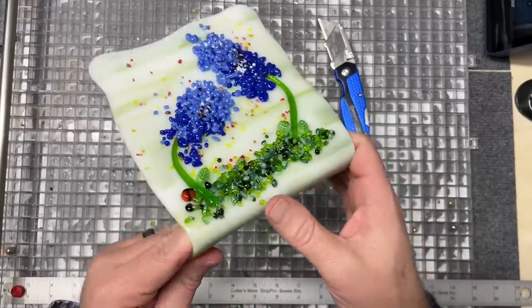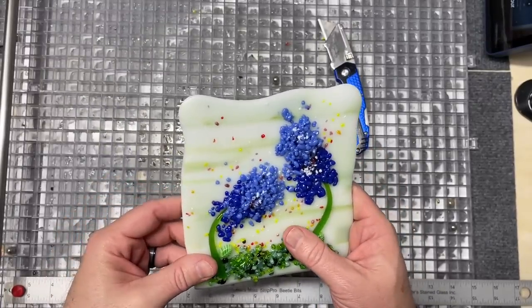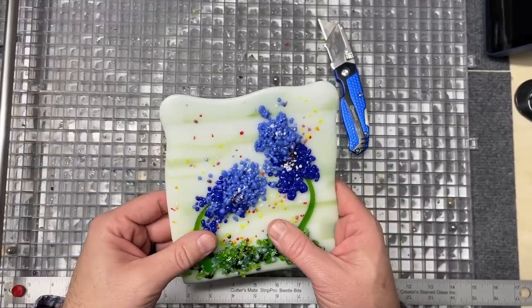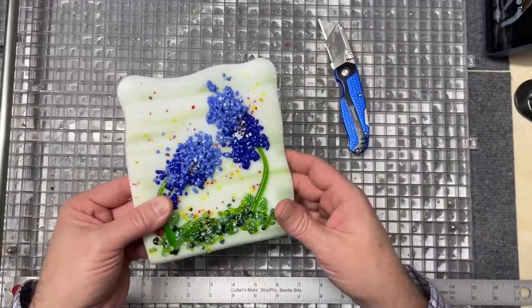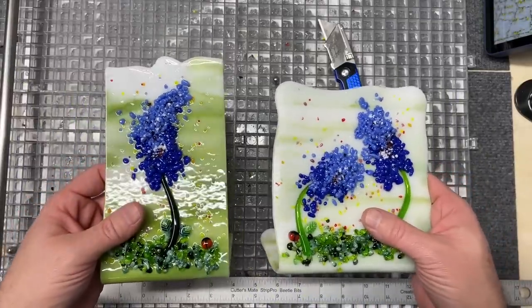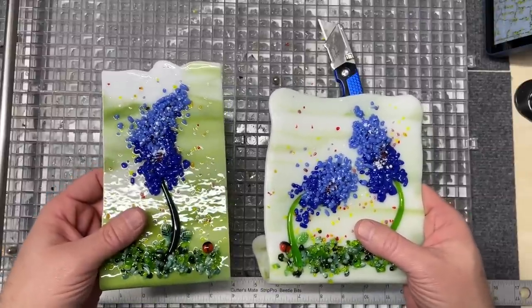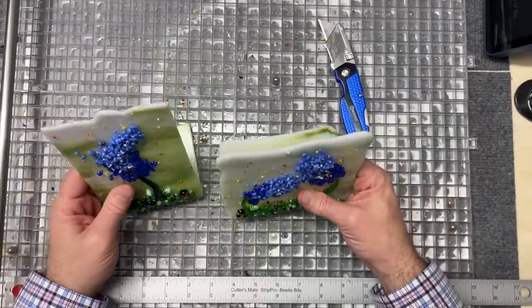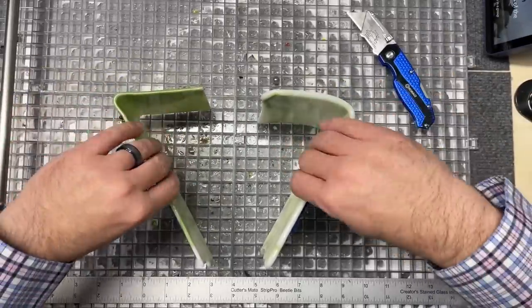We're done — here is the self-standing piece, folded over quite nicely. My firing schedule will be in the video notes as always. I have to admit when I opened the kiln I had a little bit of a panic attack — that's a stainless steel former and I forgot to put any kiln release on it. I usually put fiber paper down but totally forgot. Neither piece stuck though, so I lucked out. It was a low slump temperature, about 1200 degrees, but I got pretty lucky — I'm not sure I'd tempt the fates again. Both pieces stand quite well.